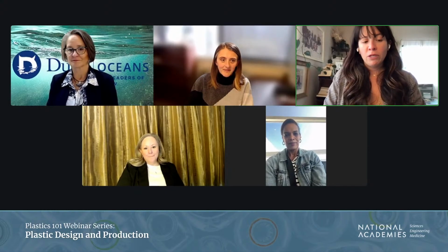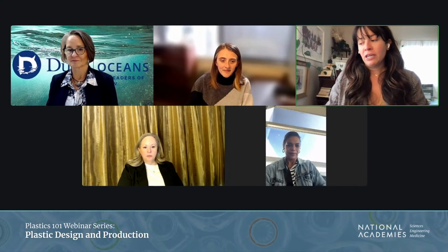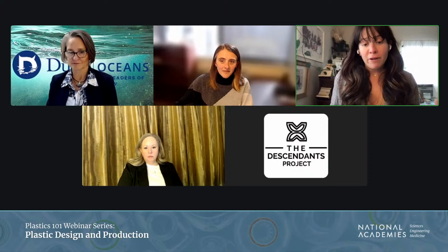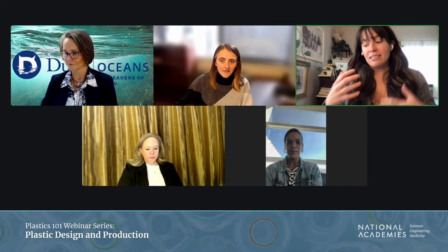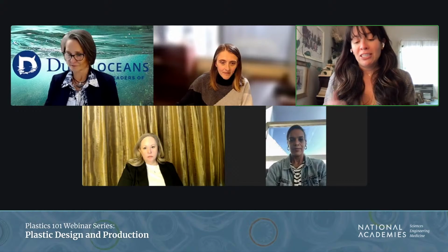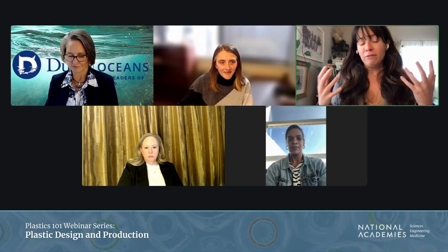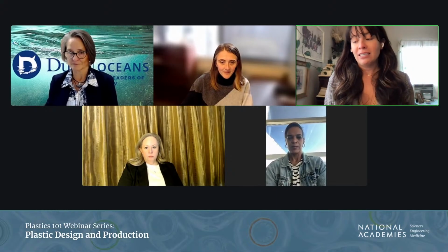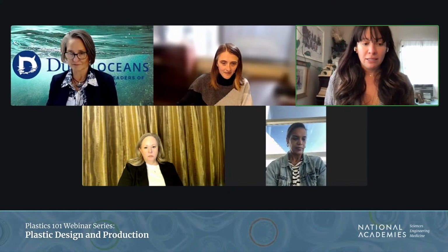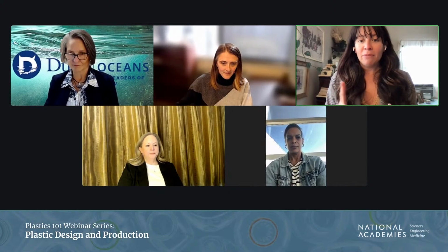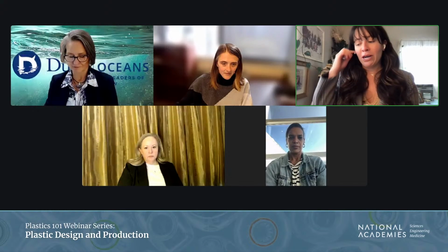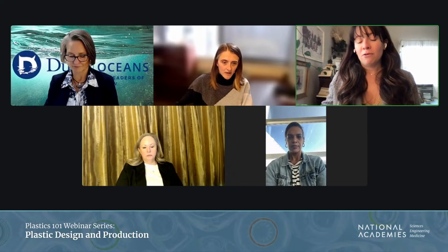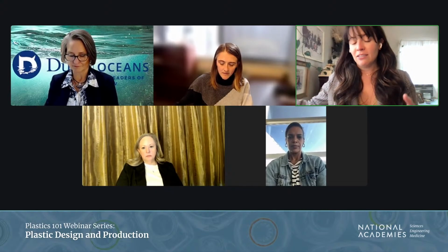I can touch on one topic that we touched on briefly earlier in the talk, which was multi-layer film production and the sachet packaging, and this is part of what Joe mentioned, the clear window for the spaghetti. We developed those materials to achieve really long shelf life of plastics, but we also developed them to be highly branded and marketed. They had to be clear, they had to be printable so that people could put specific branding on there. And those things that we achieved for visual appearance have also created materials that are less and less recyclable.